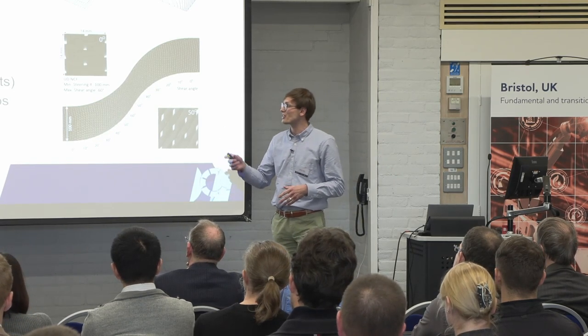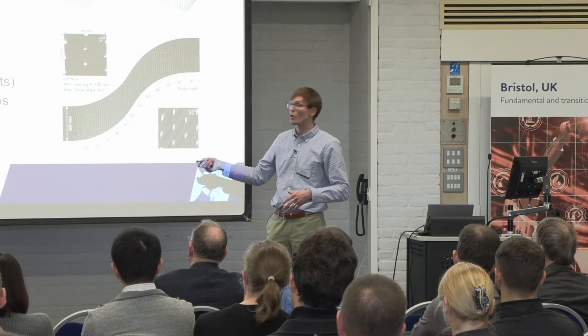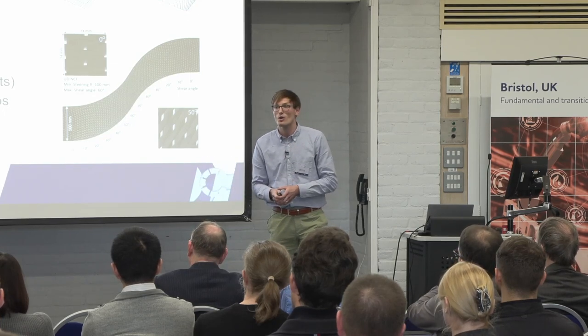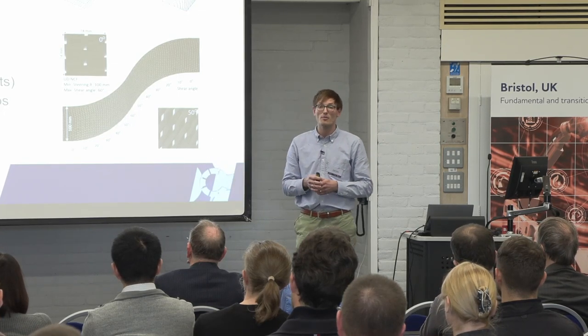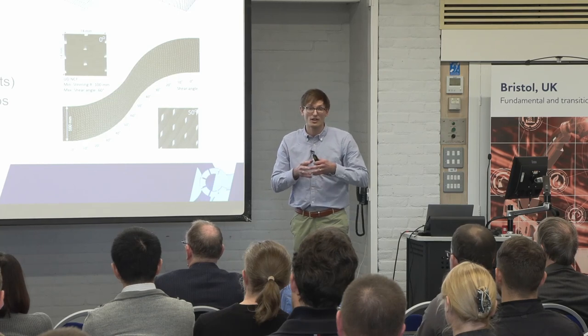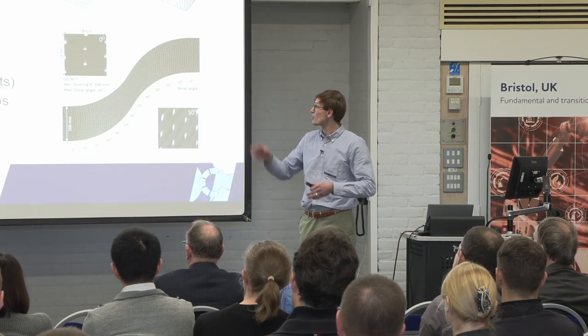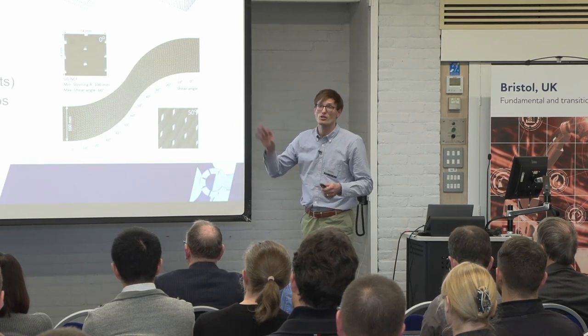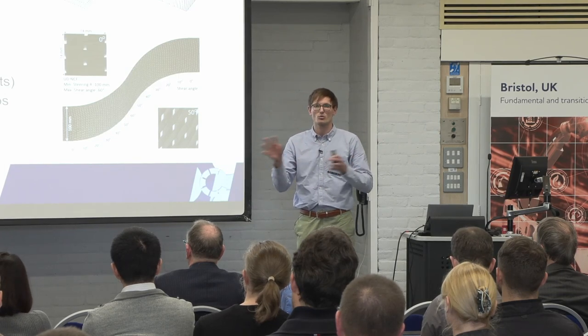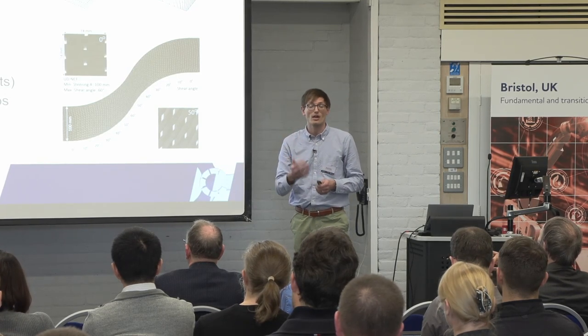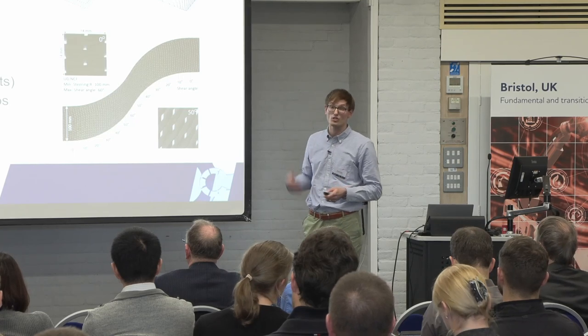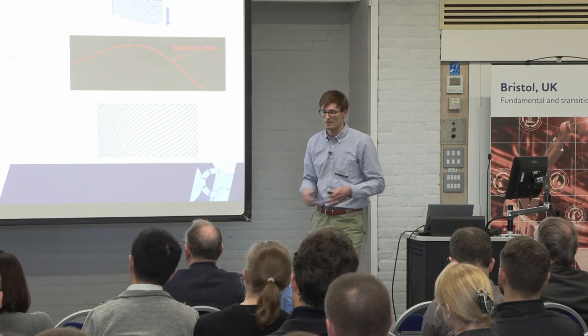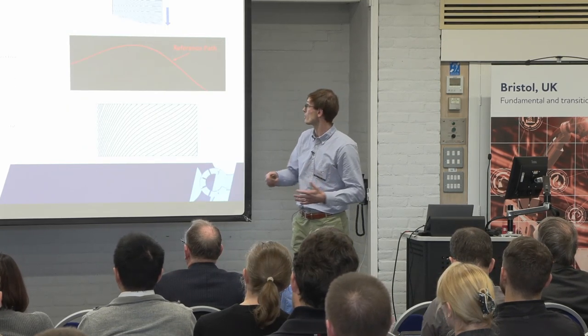Now, what we were interested in here is the redistribution of load paths. Generally speaking, when you have a displacement-controlled experiment, the load will follow stiffness. And so by playing around with the fiber distribution, we could tailor which parts of the structure were stiffer than others. And that was really what enabled us to design more robust fiber-steered structures.